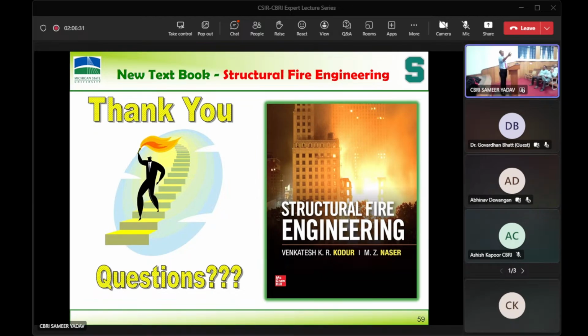Many wood columns, for example, we have used a lot of wood. It can last 2 hours in fire without collapse. A steel column collapses in 20 minutes. I can give you about 100 cases where fire behaves against everything we think. Steel stud walls, if you put fire insulation, do very badly in fire. Remember, this is fire protection insulation. Whereas if you leave that without insulation, heat comes and goes away. If you put insulation, heat gets trapped between the 2 studs and it damages the studs in 20 minutes in local cooking time. So there are a lot of anomalies. So I think it's very hard to include everything.